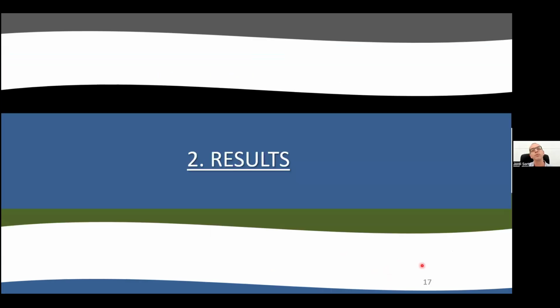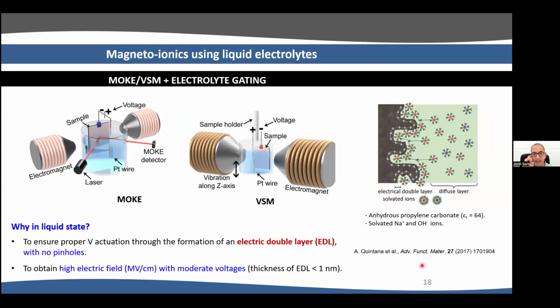Okay, now I would like to show what we have done in the last seven or eight years on this topic. I will start by mentioning that many times we use what is called electrolyte gating. That means immersing our material of interest, most of the time, in a liquid, in which the liquid is able to generate what is called the electric double layer, which is an ultra-narrow dielectric that surrounds the whole material. Even if there is roughness, it just conformally coats the interface between the solid and the liquid. And this electric double layer, which is very narrow, allows creating extremely high electric fields at the surface, of the order of megavolts per centimeter.